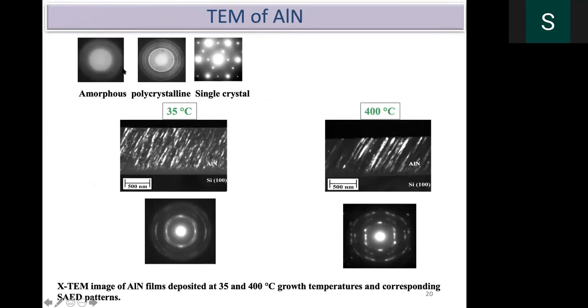If it is amorphous, a diffuse ring can be seen. For a polycrystalline material, this is the selected area diffraction profile. The rings, perfect rings, mean all the orientations are randomly oriented, which means polycrystalline. When you grow a perfect single crystal, you will see only spots at definite places. But in this case, it looks like a polycrystalline.